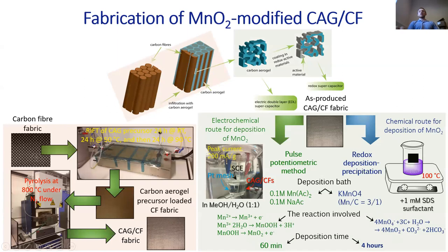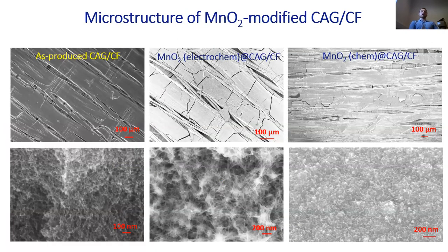They have a different time scale, where the first electrochemical approach requires only 1 hour, and the redox deposition through precipitation needs 4 hours to finish. Comparison of the microstructure of electrodes before and after manganese oxide deposition shows that our vacuum-assisted infusion of carbon aerogel precursor enables us to form a very thin and compact layer of the carbon aerogel on top of the carbon fibers and between the pores, where the microstructure consists of a network of small carbon particles interconnected into mesopore channels of different sizes. The deposited manganese oxide by different methods actually shows slightly different morphology and microstructure.